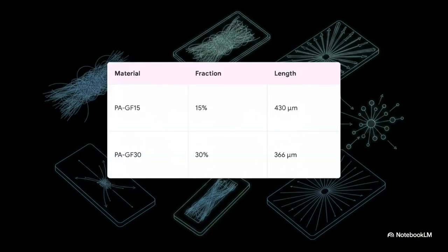But to truly prove real-world applicability, the researchers didn't just stop at digital simulations. Here we have a table highlighting experimental validation data from the literature, testing the network against physical glass fiber reinforced polyamide 6 composites, specifically PAGF15 and PAGF30. These were real-world plates that had complex orientation distributions. Now, while this table gives you the basic parameters, the researchers actually used figures 13, 14, and 15 in their study to graph the ANN's exact performance against this experimental data across various cut angles relative to the injection flow. And guess what? It successfully and accurately predicts the real-world lab tests. No way around it. It just works.